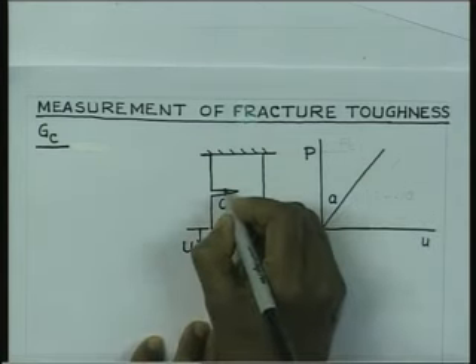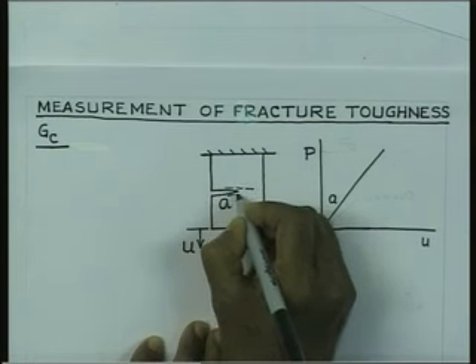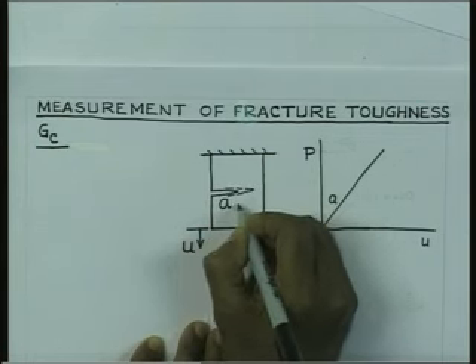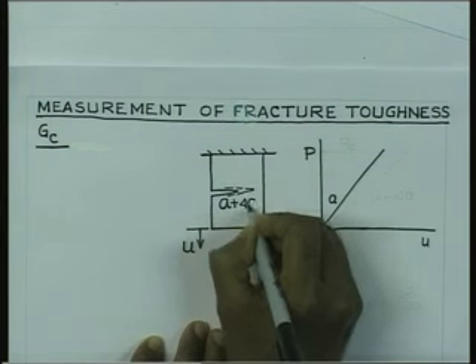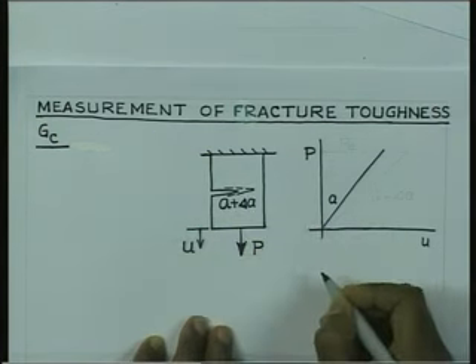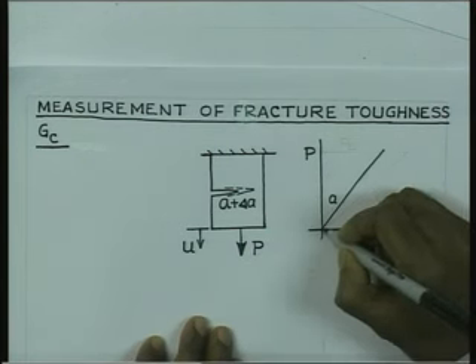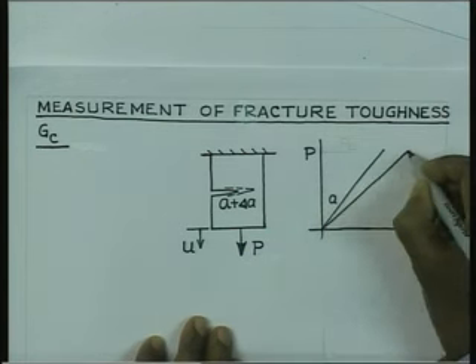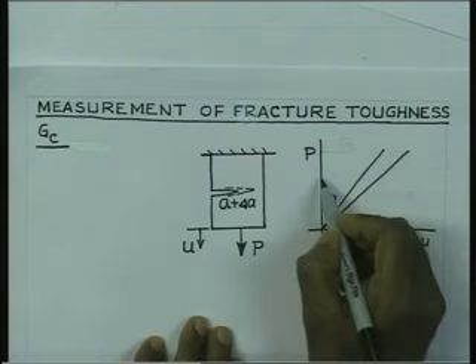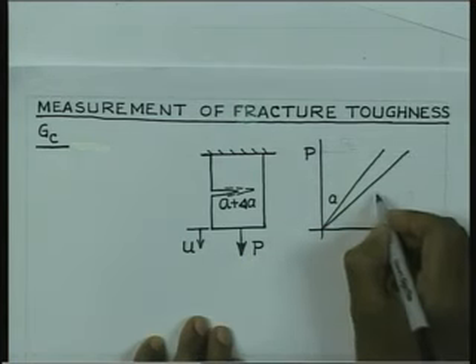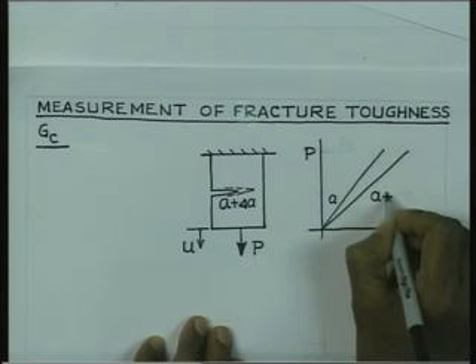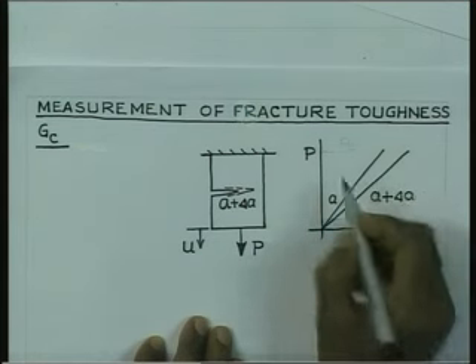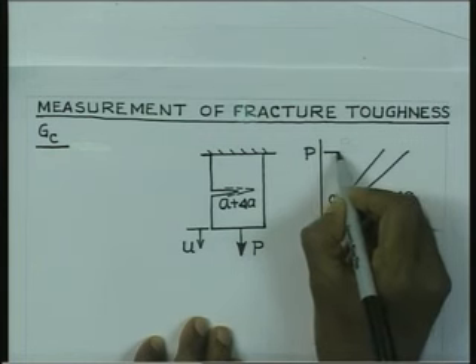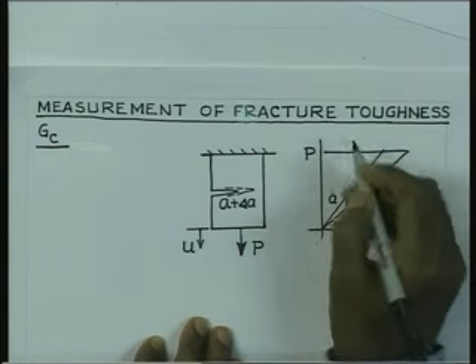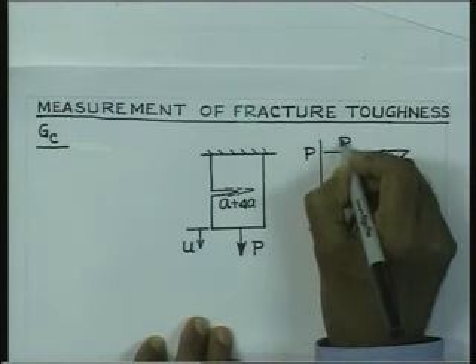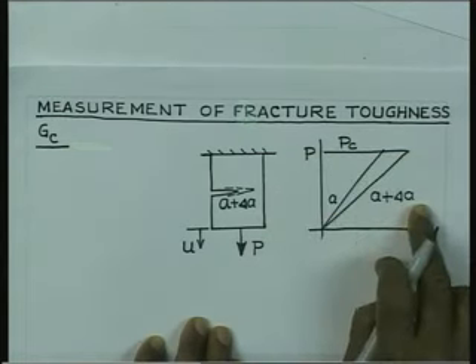If you consider a crack of a larger size, let us say a plus delta a, and we try to plot the load versus deflection, you are going to see now a variation of this type. Here for the same load you are expecting larger deflection because there is a crack of larger size. At the critical level of the load, when P reaches critical level, you are going to see extension of the crack from length a to a plus delta a.